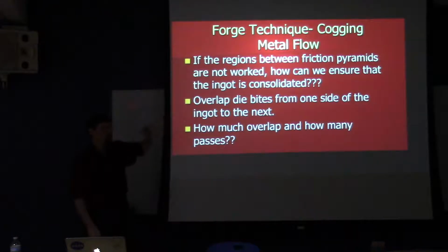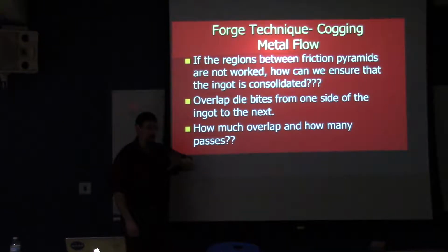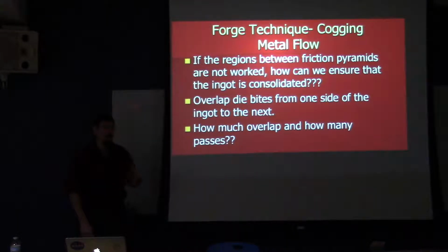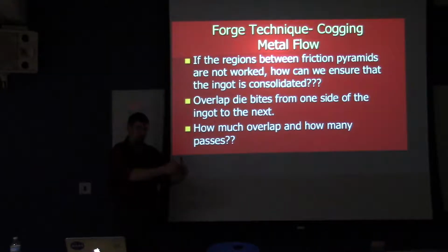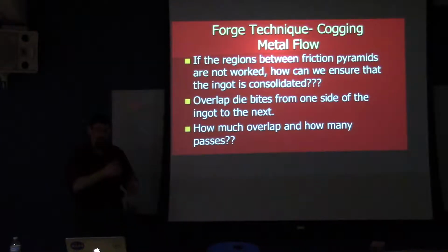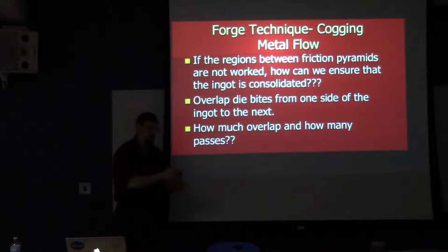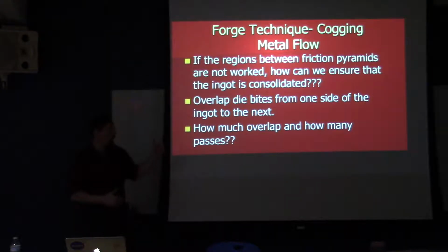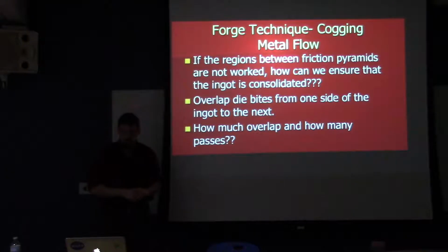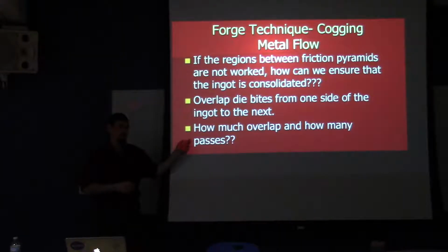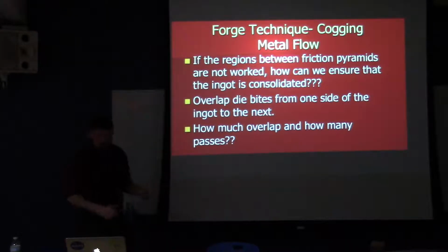Typically what we would do is we would make a pass down the length of the ingot, and then we would rotate the ingot 90 degrees and we would make another pass. And so it would be pass number 2, which would be sort of staggered or offset a little bit from pass number 1. And then we would make a third pass after rotating 90 degrees, and that would be offset yet again. And we would continue to do that until we've worked the metal all the way down to the size that we need. But this kind of begs the question of, if we know we have to do that, can we quantify that and predict that so that we can set up a procedure that we know is going to be effective? And the answer is that yes, we can do that.